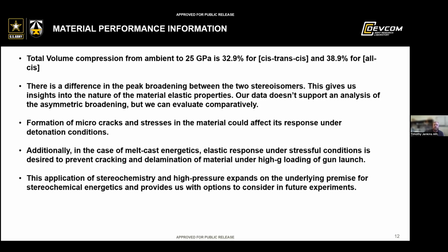And couple that with the material response to the pressure, and the fact that we notice significantly more broadening of the cis-trans cis, indicates that potentially this material might develop more micro cracks and stresses than the all cis. This allows us to potentially apply this understanding to how this material will respond under higher stress conditions. Mainly, we don't want to see, in a high G gun launch environment, something where we have cracking or delamination of the material under a load or a shock load or something like that.